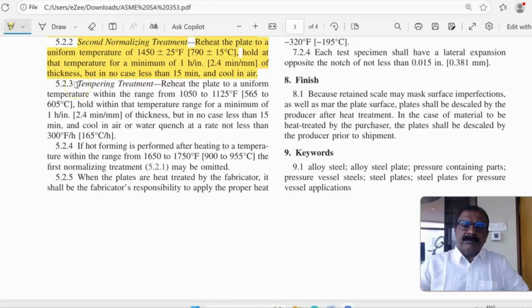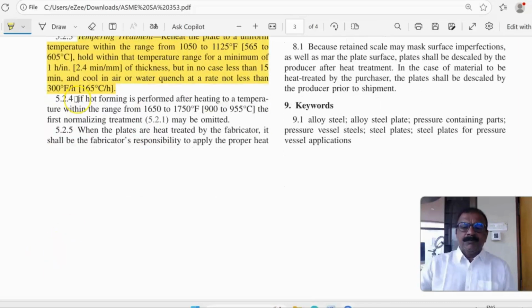After 2 times normalizing, now tempering treatment. Reheat the plate to 565 to 605 degrees centigrade and hold within the temperature range for a minimum of 1 hour per inch of thickness, but at least 15 minutes, and then cool in the air or water quench at a rate not less than 165 degrees centigrade per hour. There is one more condition. If hot forming is performed for dish ends and reinforcing pads, after heating to a temperature of 900 to 955 degrees centigrade, then the first normalizing treatment given in 5.2.1 may be omitted.